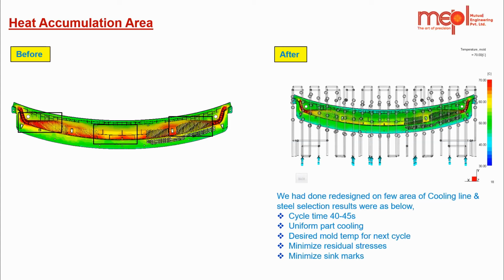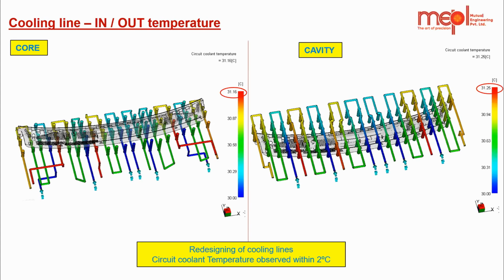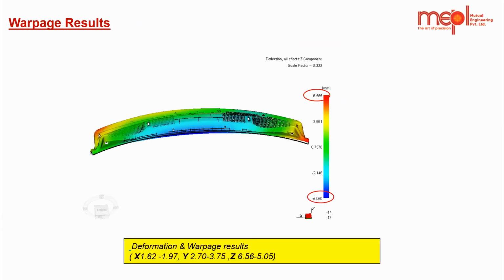After modifying the cooling, we achieved a cycle time of 40 to 45 seconds. We can see uniform part cooling and the desired mold temperature for the next cycle, and even minimized residual stresses in the part. After changing the cooling line, the in and out temperature of the coolant is within 2 degrees Celsius. We could also reduce the warpage results. Before, the warpage was very high, and after providing uniform cooling in the mold, it helped reduce the warpage and deformation of the part.